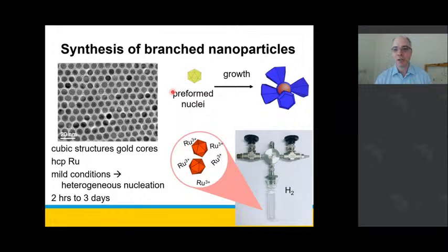Typically when we're doing these reactions, we leave them cooking for hours or sometimes days. So it really does give you an indication of how slowly we're decomposing our second metal precursor.